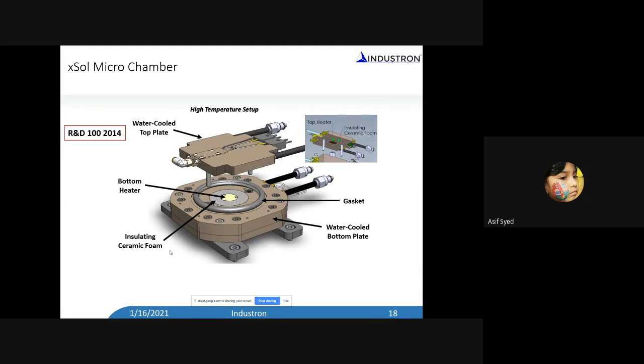In this construction, we design it in a way that the thermal expansion of one cancels the other's. So the net thermal expansion in the Z direction is only 6 nanometers per degree C. With that, we were able to have nanometer length scale stability. At the same time, we can go to temperatures as high as 1000 degrees C, as cold as minus 120 degrees C, so that we were able to change the temperature from cryogenic to very high temperature up to 1000 and still be able to study the nanomechanical properties of material and its response at different temperatures.